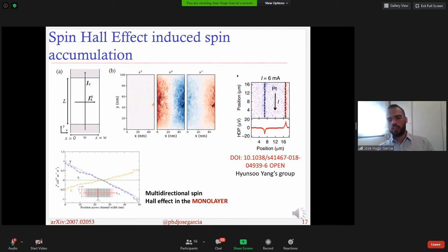Actually, for this plot, and for the spin relaxation length and for the quantum spin Hall insulating state, you can always trace the relative value of the spin polarization to the spin texture. And this is due to the fact that the spin texture is a persistent spin texture. So in MoTe2, the spin texture is mostly in the Y direction, so everything in the Y direction is larger, and in tungsten telluride it is mostly in the Z direction, so everything in the Z direction is high.